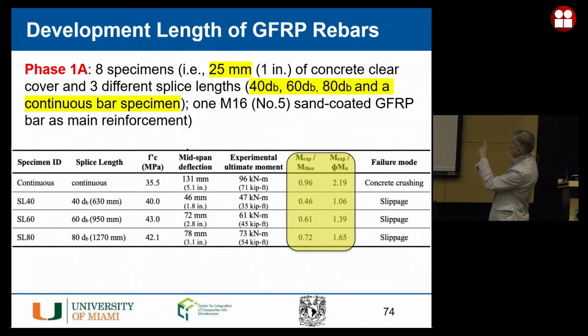The 25 millimeter is the cover, and the bar is a number 5, an M16. These are sand coated, and then we test three splice lengths: 40 diameters, 60 diameters, 80 diameters, and obviously the bar one is continuous. By the way, if we were to use development length for a splice without any safety factors, the number of diameters would be close to 150. So we're much lower than that, just to see the effect.